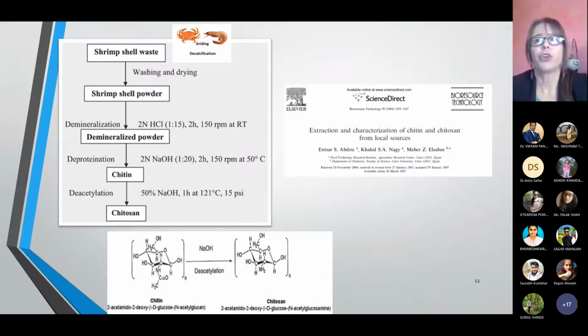When we have the absence of color in the medium at the end of the last treatment, then we will proceed to washing with distilled water. This was carried out up to neutrality, after which the samples were dried. At this stage, pigments responsible for the color are removed using a mild oxidizing treatment. Ethanol was also used to eliminate traces of protein and coloring materials. At these steps, we will obtain only chitin, which is a biopolymer, and it is widely used, for example, as an additive in food.